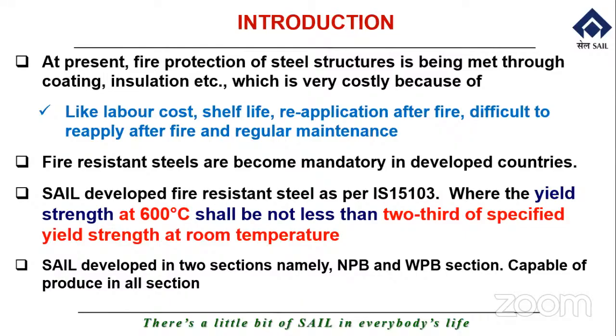Fire resistant steels have become mandatory in developed countries, and SAIL has developed fire resistant steel as per IS 15103, where the yield strength at 600 degrees centigrade shall not be less than 2/3 of the specified yield strength at room temperature. So SAIL has developed it in two sections, namely NPB and WPB sections, capable of being produced in all sectional